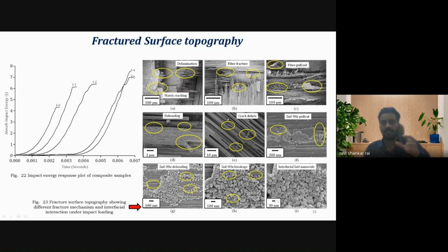After that, the entire broken sample has been analyzed, and a couple of images have been mentioned here. Here you can see different sets of fracture surface topography. The delamination is there, matrix cracking is there, and the fiber fracture is there. Initially, without nanostructure, these structures were seen, and the fiber pull out also. Once the nanostructure has been developed, we can see the debonding of the nanostructure, crack debris, and the ZnO nanostructure pull out and ZnO nanostructure debonding.